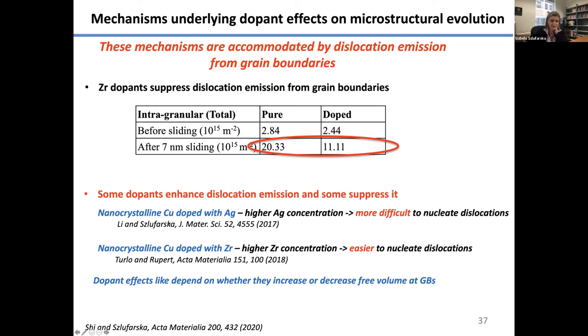So an example of our earlier study, when we look back on nanocrystalline copper doped with silver, we found the silver suppresses dislocation nucleation. Another group, on the same materials but doped with zirconium, showed that the dopants can make it easier to nucleate dislocations. So it appears that the outcome, whether dopants increase or suppress dislocation emission, is related to whether dopants increase or decrease the free volume of the grain boundary. So there are some details there, but the bottom line is that this finding provides a potential principle for design of these nanocrystalline metal alloys.